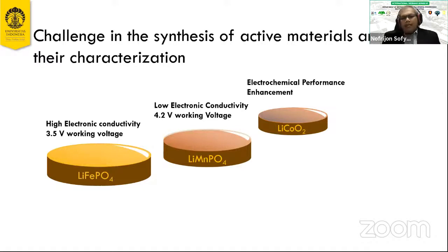But each of these materials has its own advantages, and of course, their own disadvantages. For example, lithium cobaltate has a high energy, but there is toxicity from the cobalt. Lithium manganese phosphate has a high working voltage, but it has a short life cycle. And for lithium ferrophosphate, we have a lower working voltage, but a much longer life cycle. So because of that, we need to compromise between these materials. So how can we synthesize better materials with better performance and of course with a better life cycle?